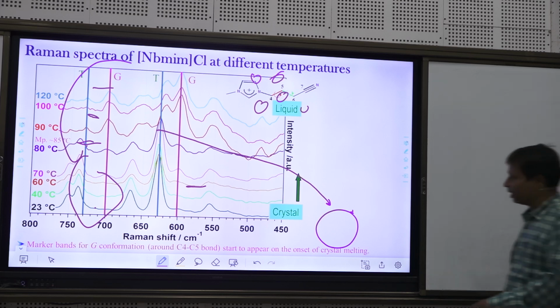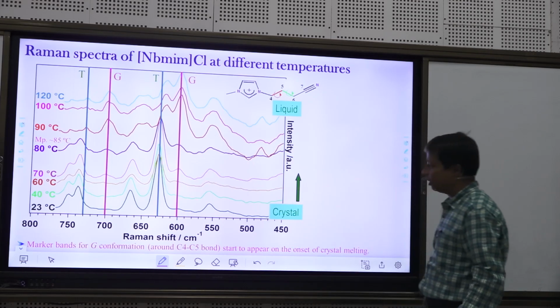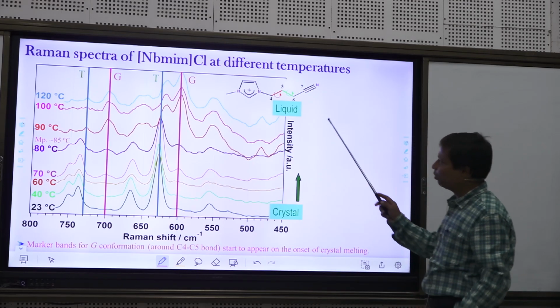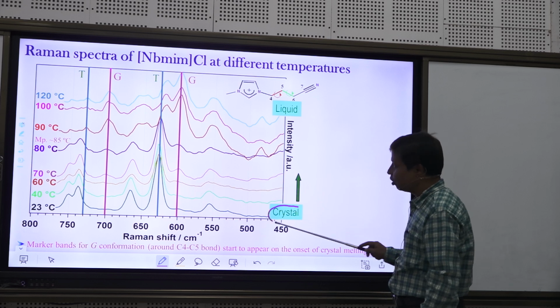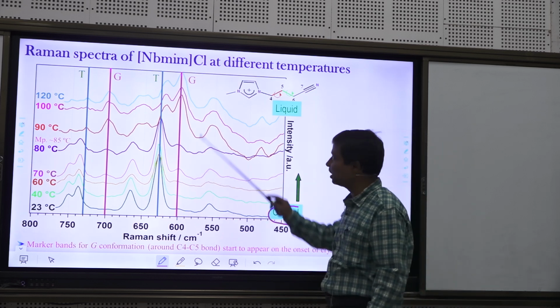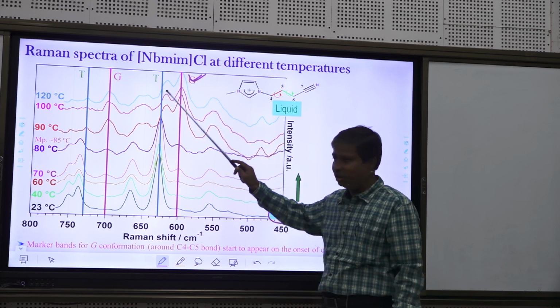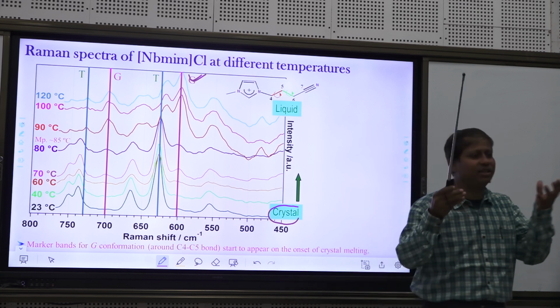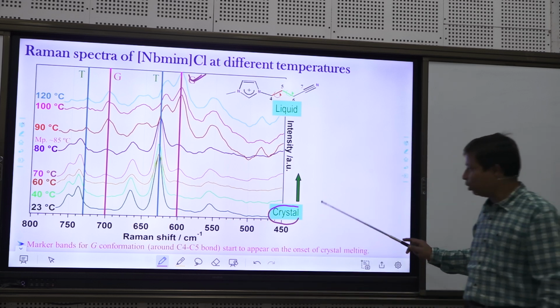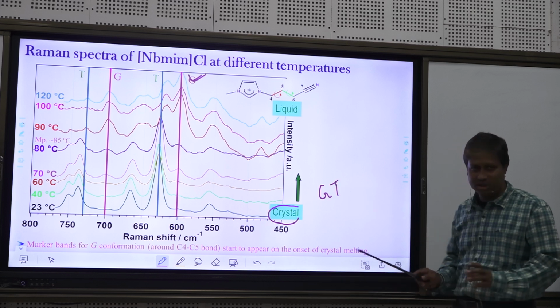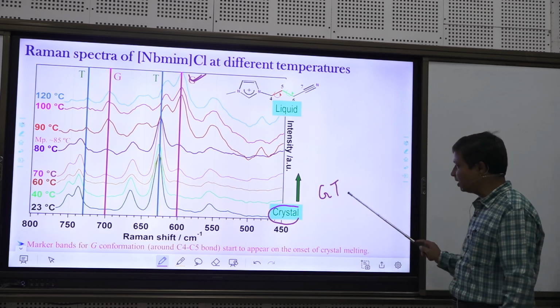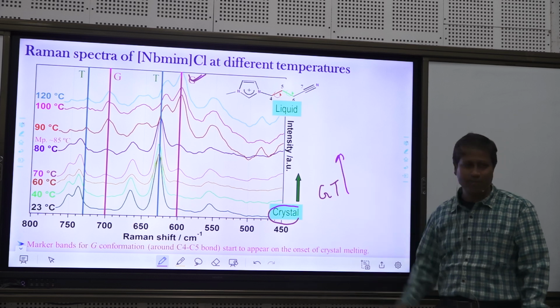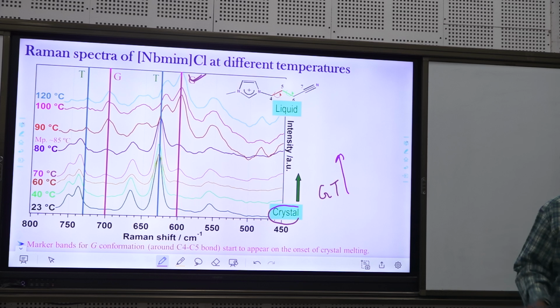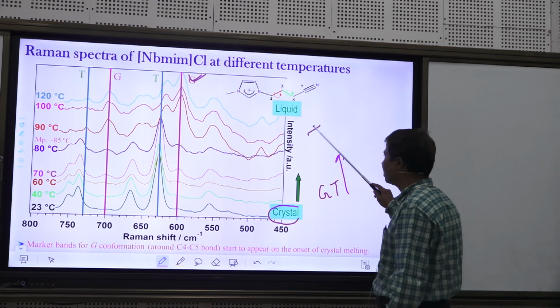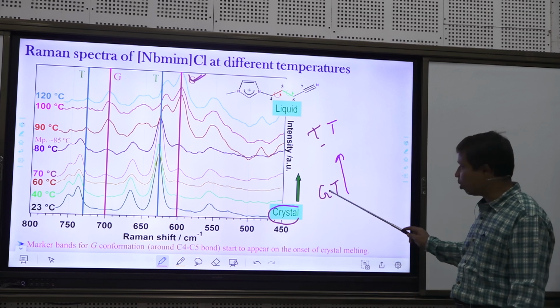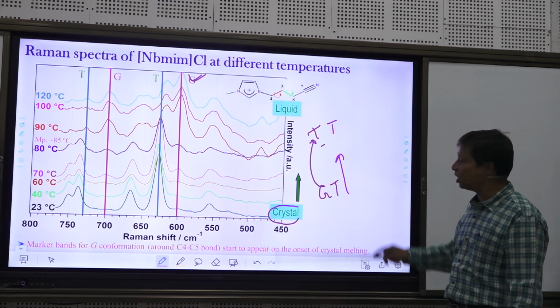This one is a temperature dependent study. There is a unique conclusion from this one. What we have done is start with a crystal that has a gauche band, a gauche-trans crystal, a pure crystal whose conformation is gauche-trans, and then we started increasing the temperature. Once it melted and became liquid, we found the arising of the trans-trans marker band. So the gauche is changing to trans.